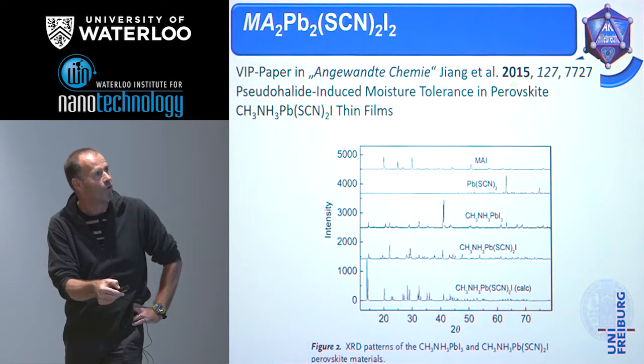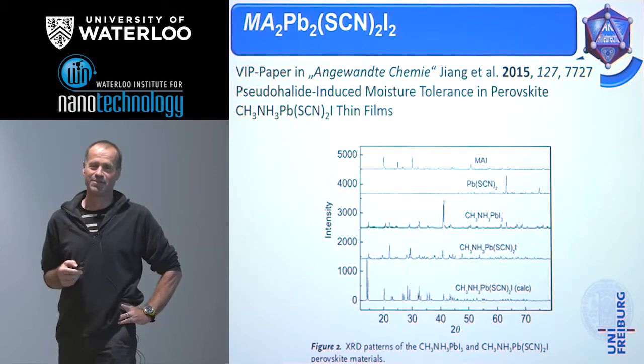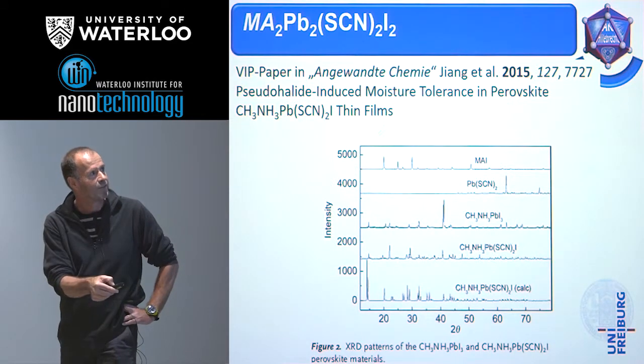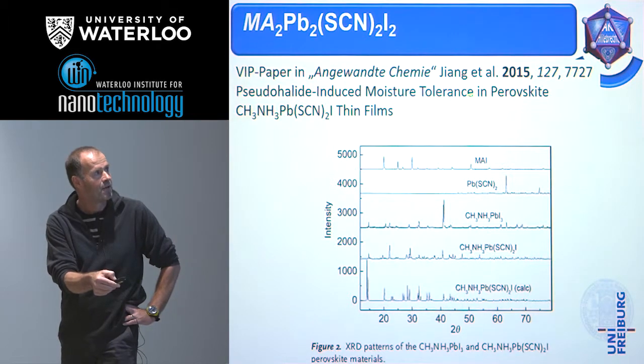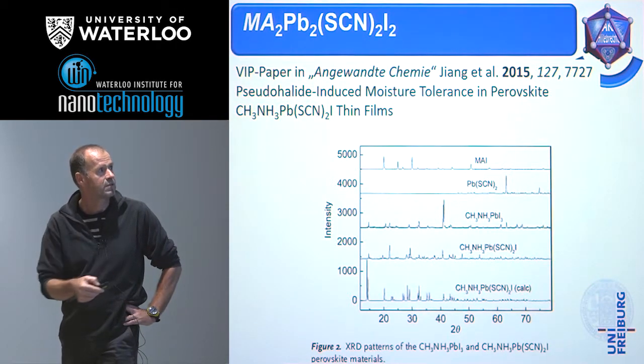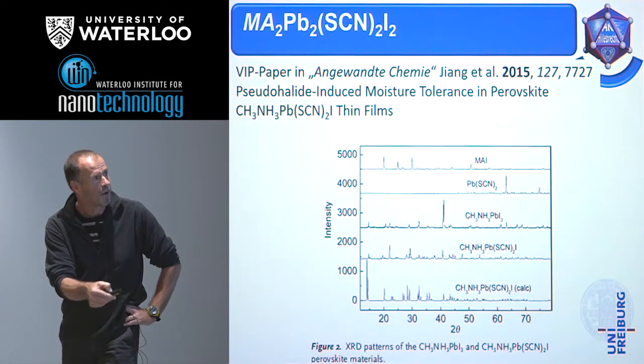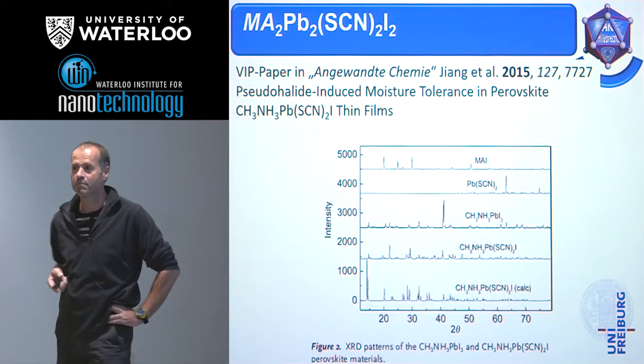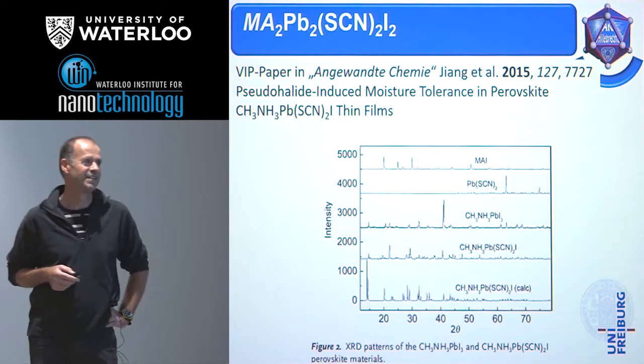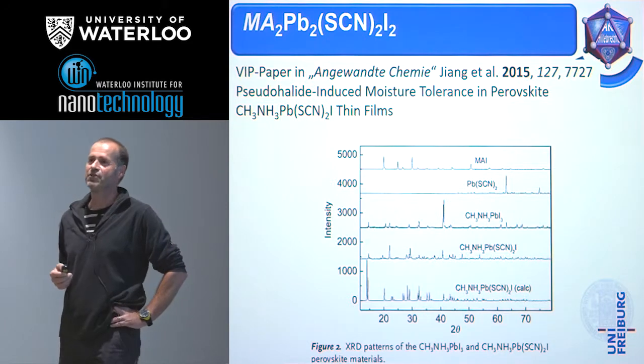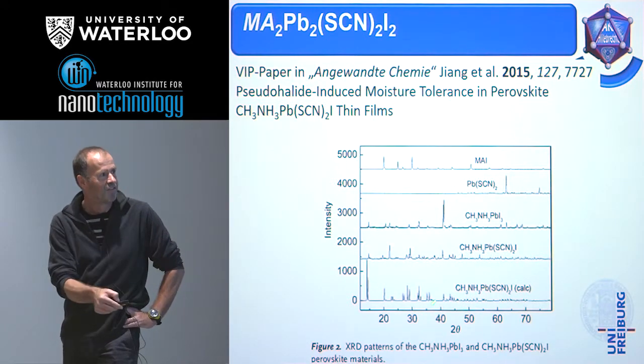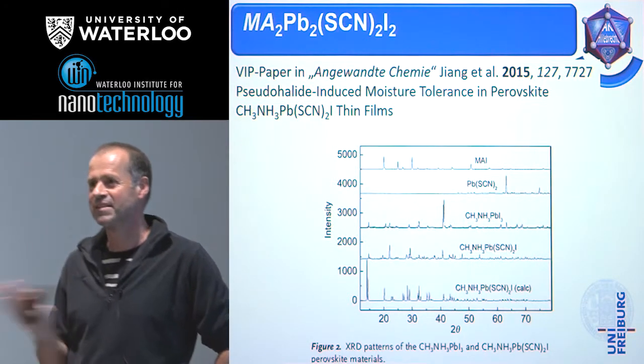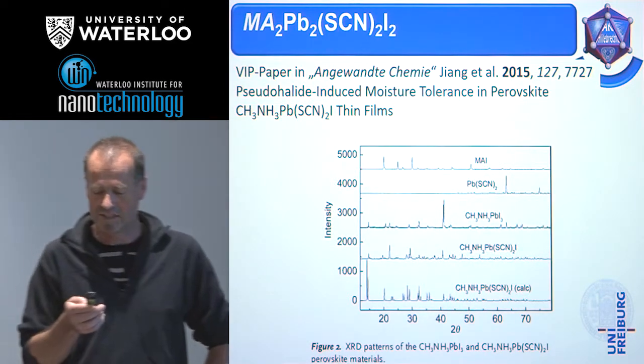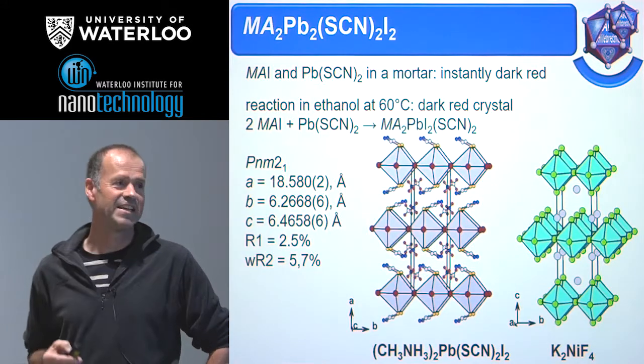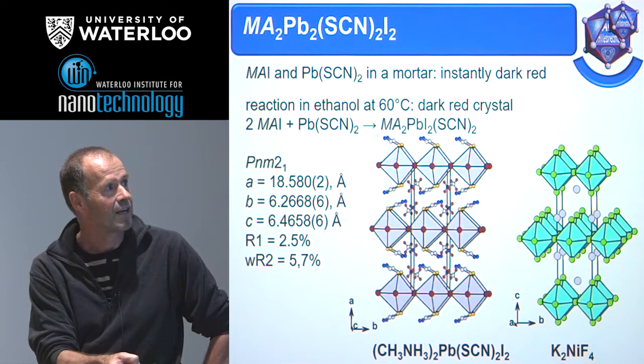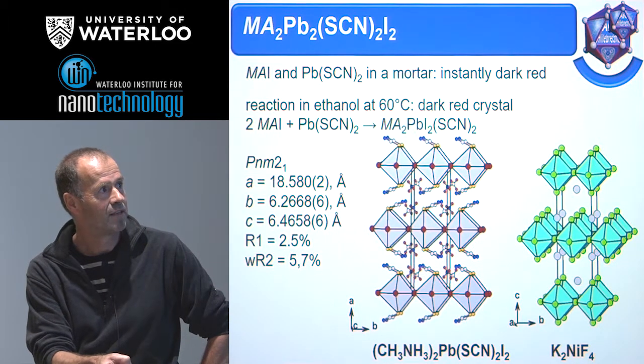Some years ago, 2 years ago, there was a nice paper in Angewandte, and it was interesting because they stated that the moisture tolerance is better if you add a little bit of thiocyanate. And then they published these wonderful X-ray diagrams, and my postdoc Michael Daub said, it's bullshit. And if you are a little bit familiar with X-ray patterns, you know that he was right. The published values are just wrong. So he said, I do it by myself. He did. He showed that the real composition is 2, 1, 2 plus 2.